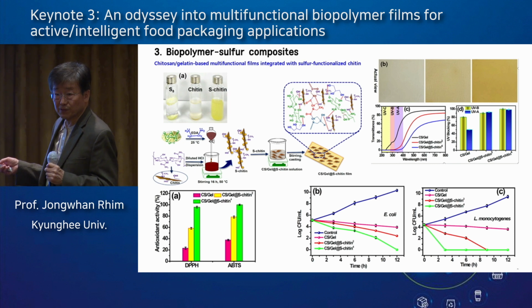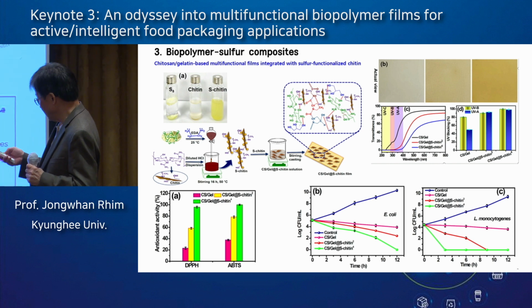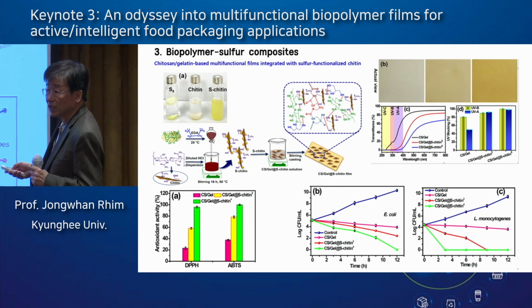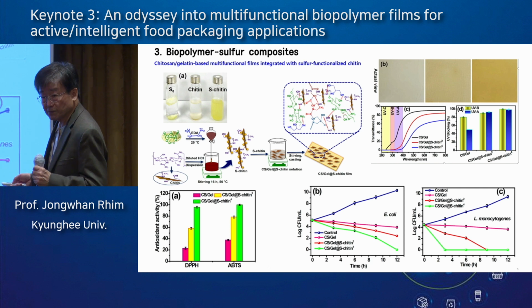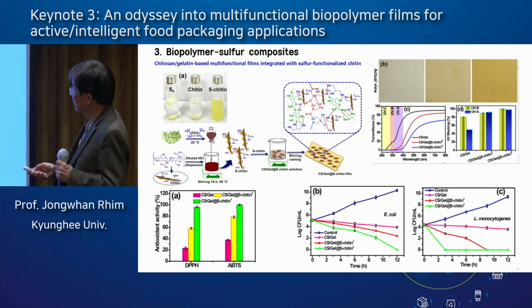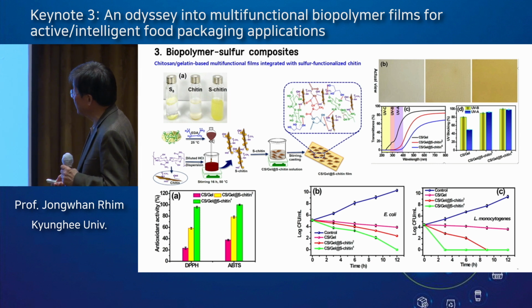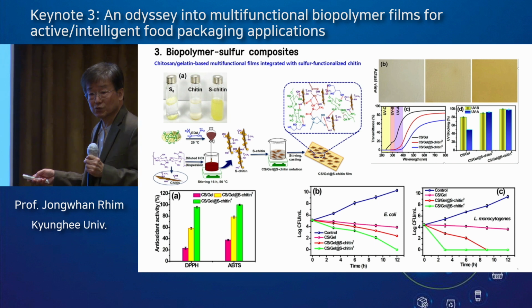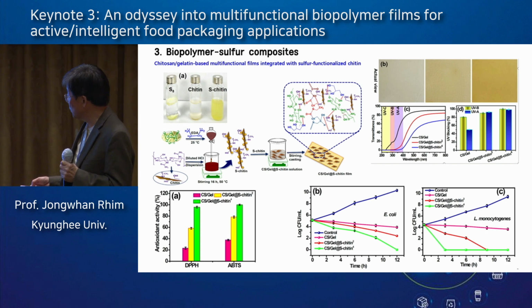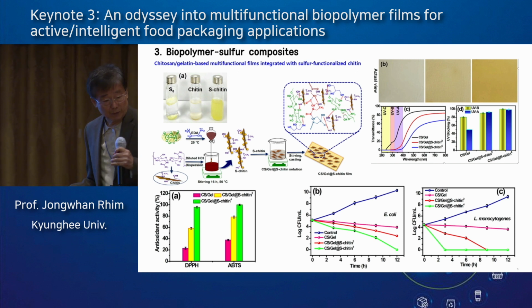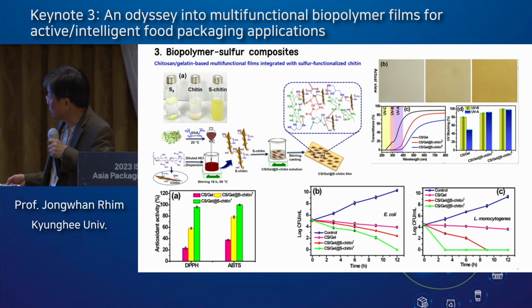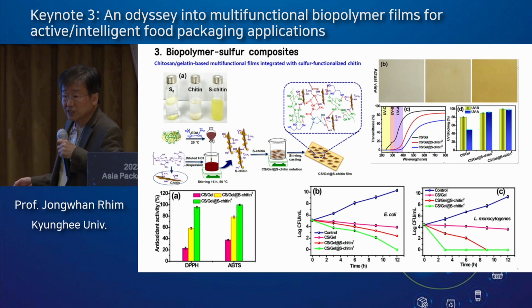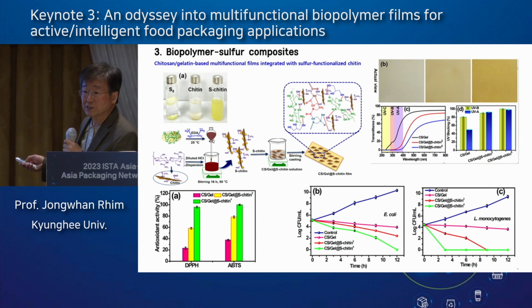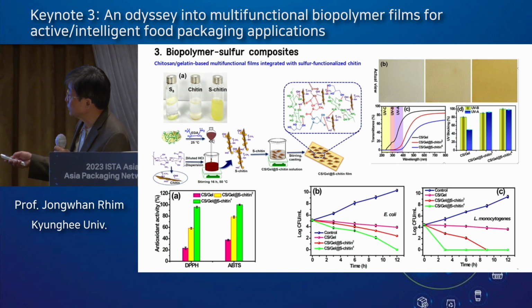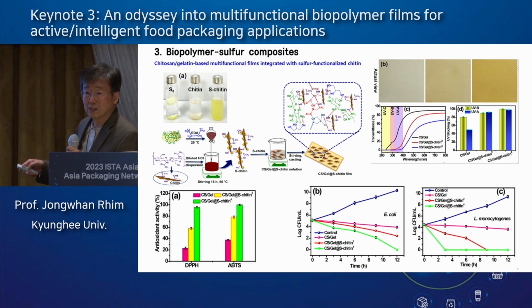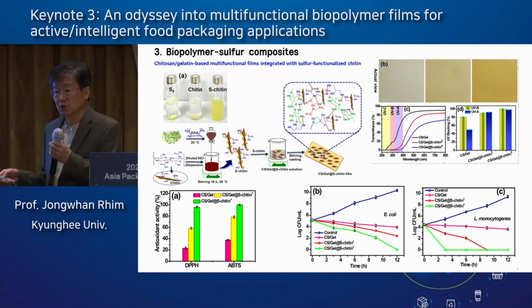Using the inverse vulcanization method, we made sulfur chitin complex. And this sulfur chitin complex was added to chitosan/gelatin films to make a composite film. This film shows strong antimicrobial activity and antioxidant activity and high UV barrier properties. It's the beginning of use of biopolymer-based high sulfur containing polymer film work.